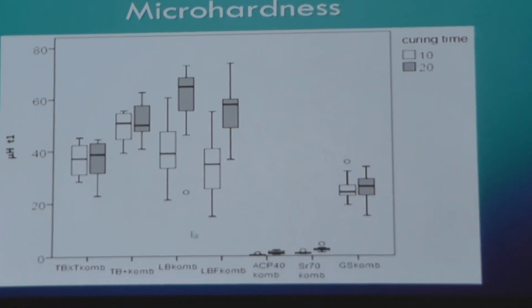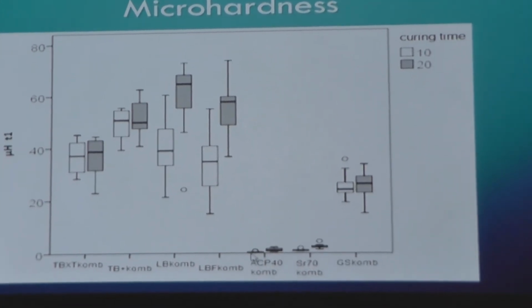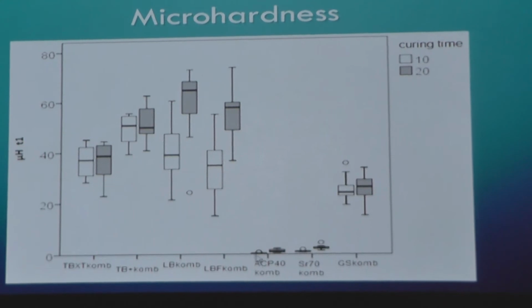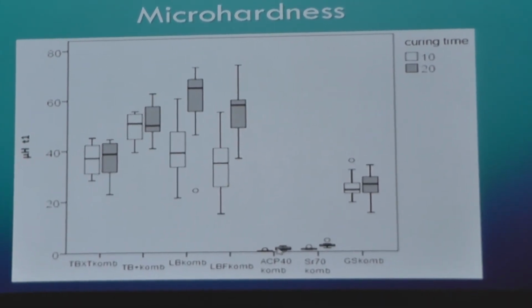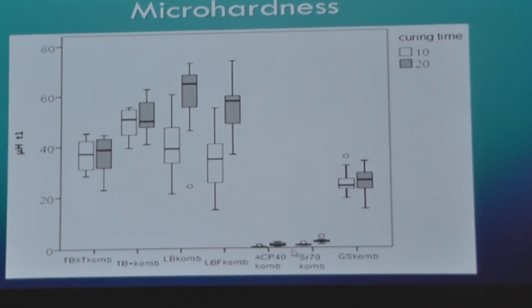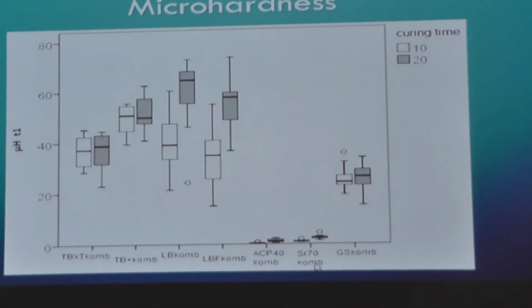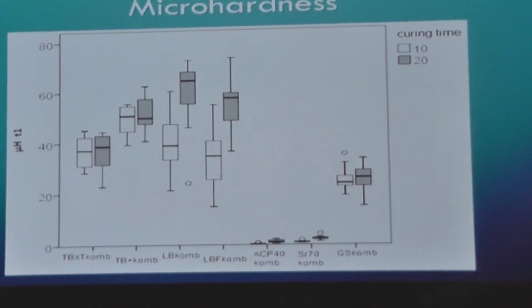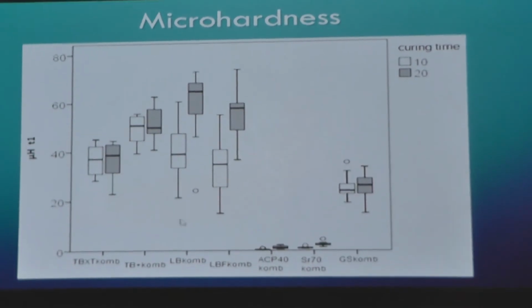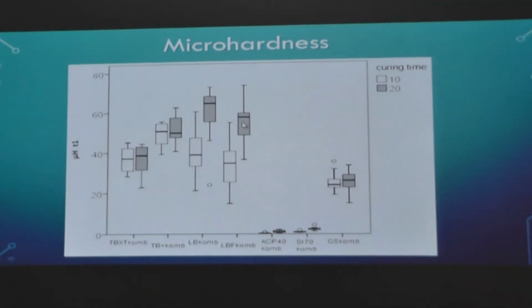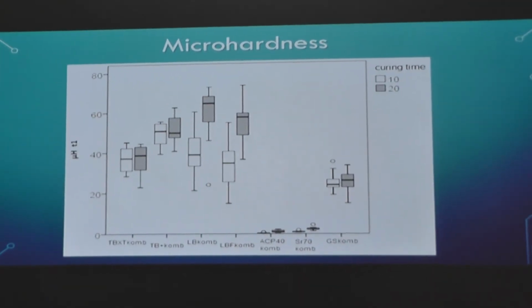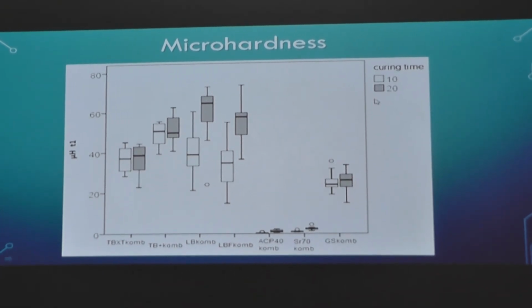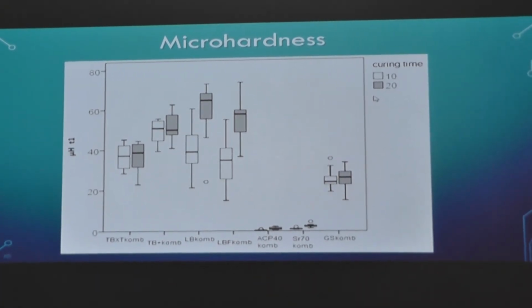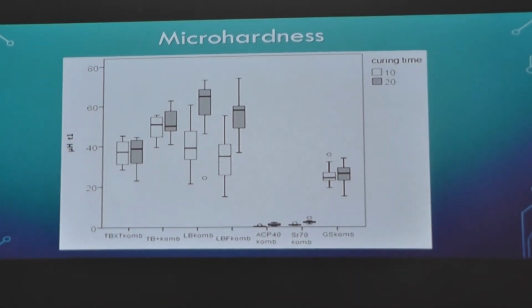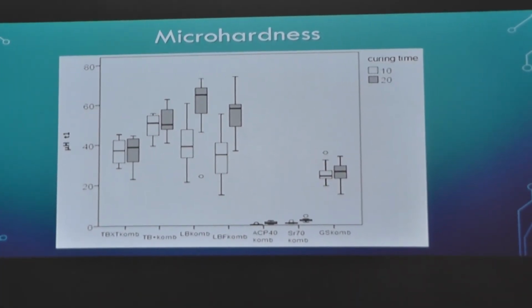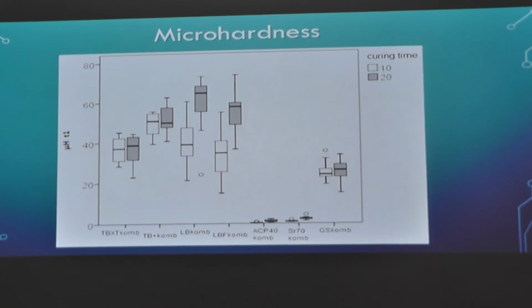When we tested the micro-hardness of the experimental amorphous calcium phosphate composite, you can see that its micro-hardness is so low that it's almost immeasurable, so it was very soft and it is not adequate for clinical use. And also what we noticed is that along with the fluoride release, the micro-hardness of these adhesives that contain fluoride decreases. So it could be that there is a problem with the structure and it is deteriorating throughout time.